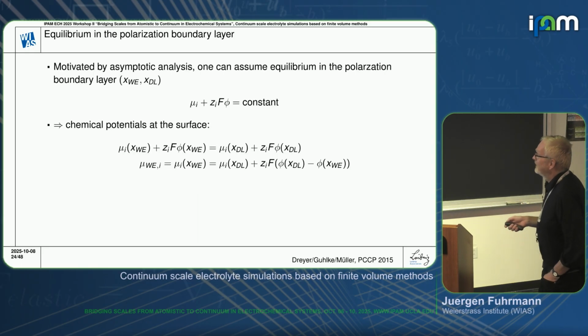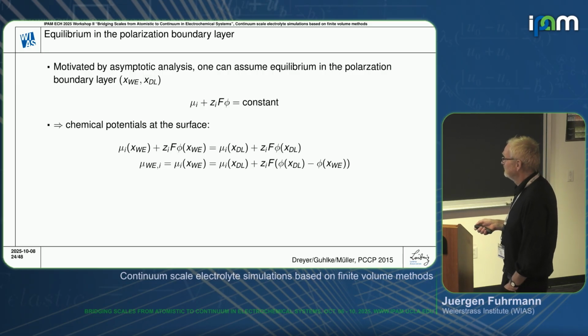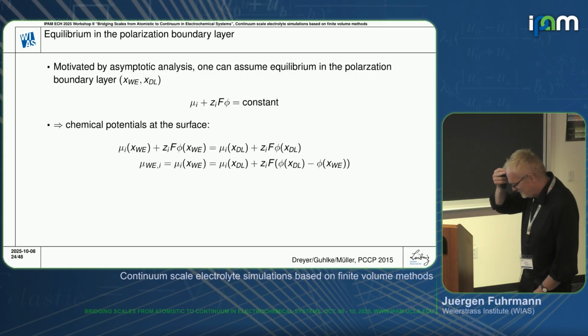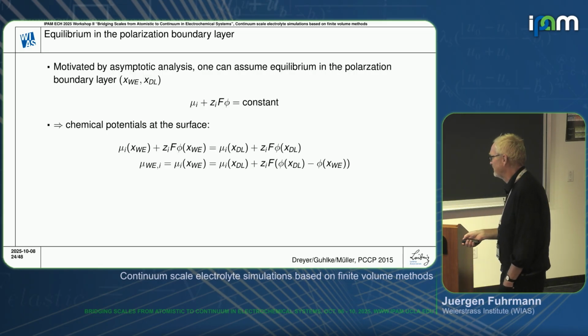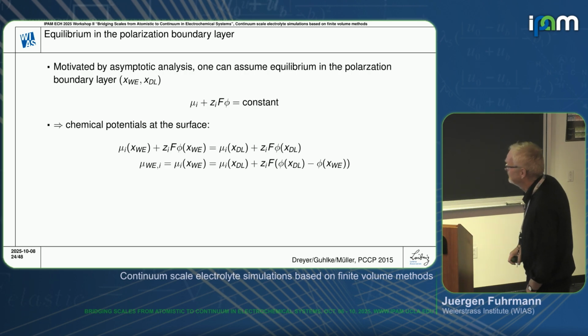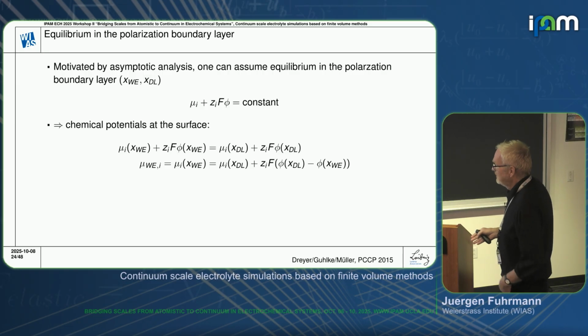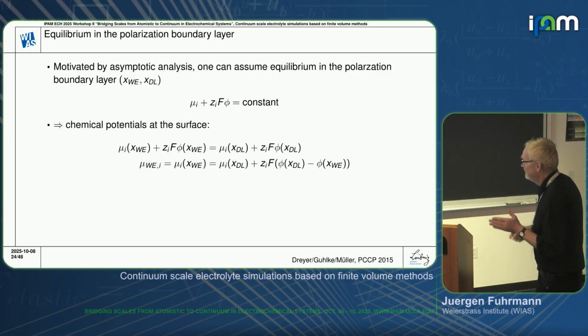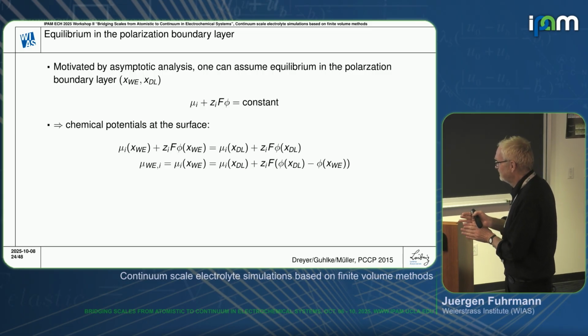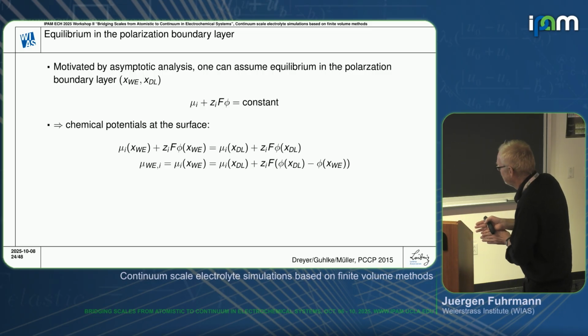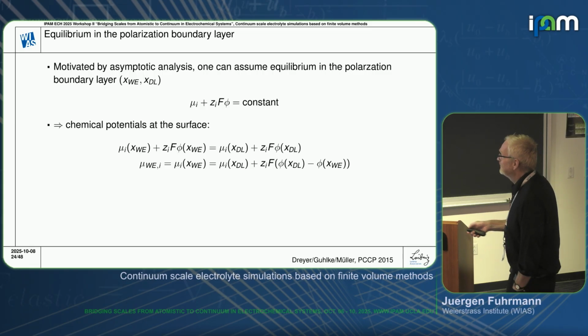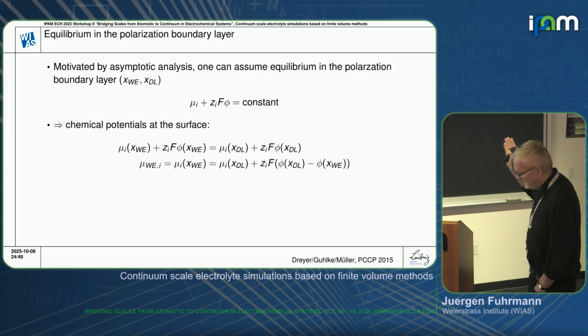If we are motivated by asymptotic analysis, one can back this in a mathematically more rigorous way. This is in the paper of Dreyer, Gühlke, and Müller in 2015, and also in the PhD thesis of Clemens Gühlke. Basically, one can derive these electroneutral equations, and the fact that we can assume an equilibrium in the polarization boundary layer, by asymptotic analysis, using the method of matching asymptotics at the interface between the double layer and the bulk. This allows us then to define chemical potentials at the surface by the values of the chemical potentials in the electroneutral domain.